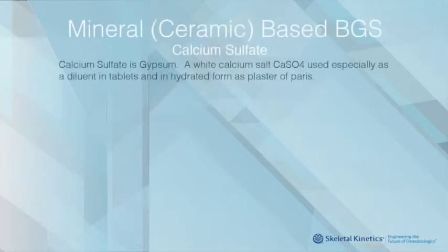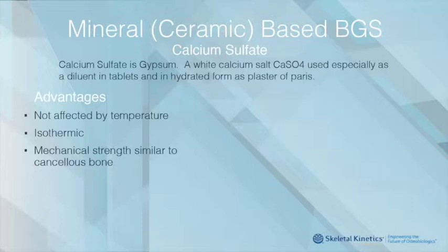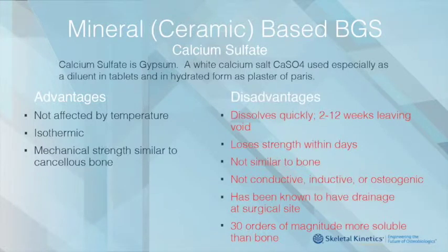In review of the other ceramic in this graft, we look at calcium sulfate, which is gypsum, or a hydrated form of plaster of Paris. The advantages of a graft like this alone: it is not affected by temperature. It is mostly isothermic, although it does have slight exothermic reaction. Mechanical strength is similar to cancellous bone early. Disadvantages include it dissolves very quickly, on average 2 to 12 weeks. Loses strength within days. It is not similar to bone. It has no biologic component. Has been known to have drainage at the surgical site. It is 30 orders of magnitude more soluble than bone.